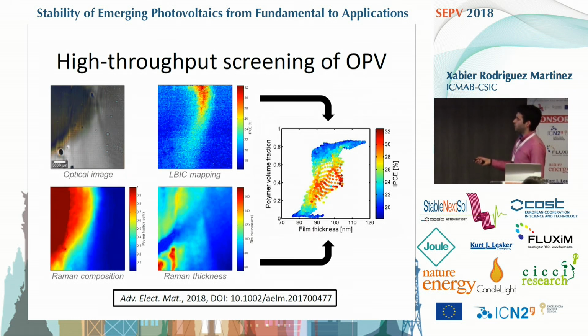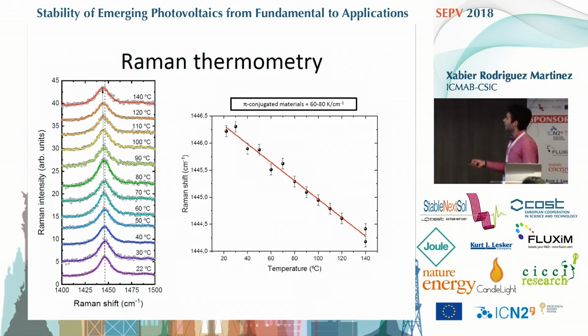And this will be part of a talk that Mariano will give just after me, in which we basically exploit this technique to do mapping of thickness and composition in solar cells, and to extract easily the optimum parameters to obtain the optimum efficiency. And just to conclude, I would also like to highlight that we are now trying to exploit Raman also as a thermometer. This means trying to infer the thermal conductivity of thin films just by looking at how the Raman modes shift as a function of the temperature.